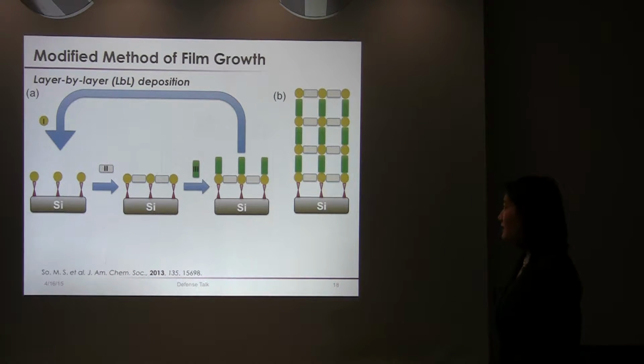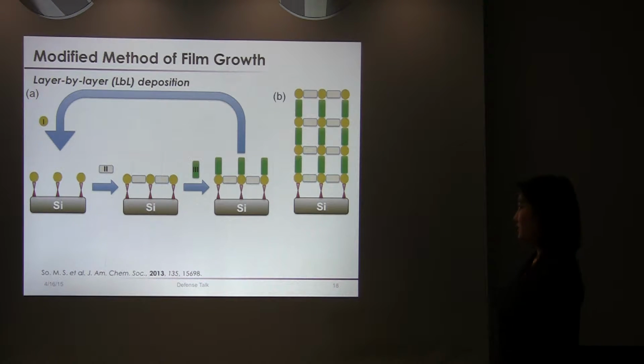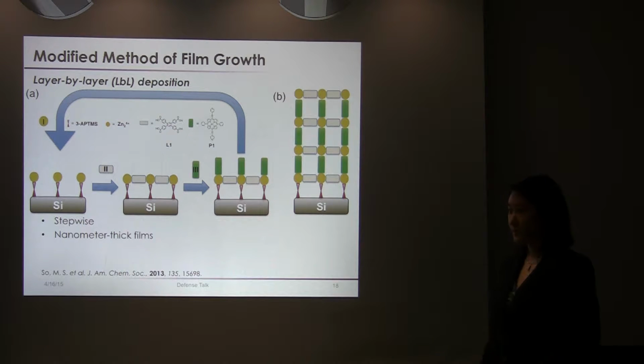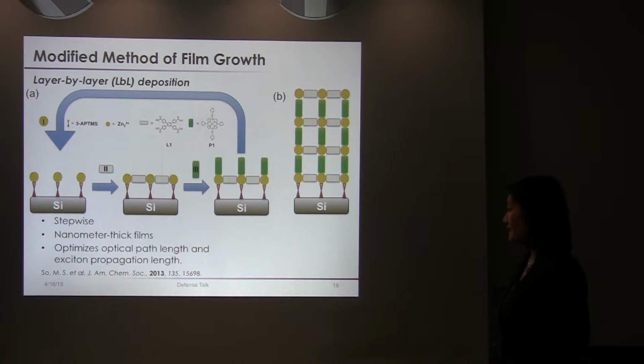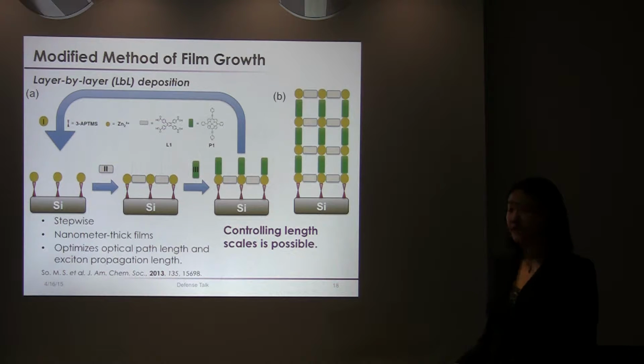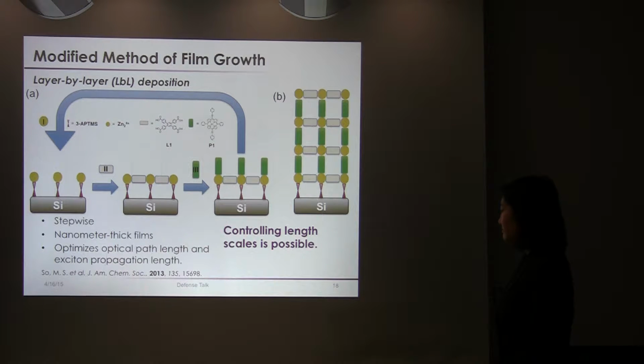So what I did was modify this method of film growth using a layer by layer approach. And essentially this LBL growth is a stepwise approach that forms nanometer thick films and can potentially optimize optical path length and exciton propagation length within a MOF film. And what this technique brings that wasn't brought before in traditional methods is that you can control the length scales very well with layer by layer deposition.